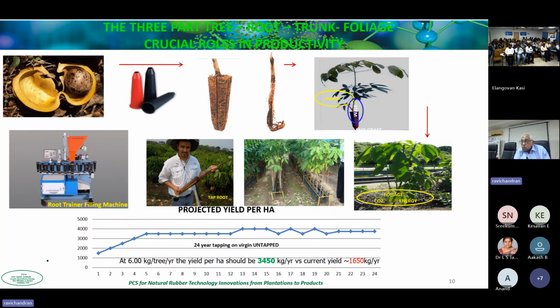And we have achieved yields of up to 3,500 kilograms in the plantation that we started in Guatemala about 15 to 20 years ago, and their yields are getting close to 3,000 kgs, whereas we are only getting 1,600 kgs in India at the moment. So there is plenty of scope to increase the yield per hectare and get more rubber from the existing plantation. So there is a real scope to upgrade the plantation's productivity and go at least from 1,600 to 2,000, 2,500 kilograms per hectare. Today, we are importing 500,000 tons of natural rubber every year. That's a shortage. Our downstream industry is growing so fast that the shortage is increasing every year.